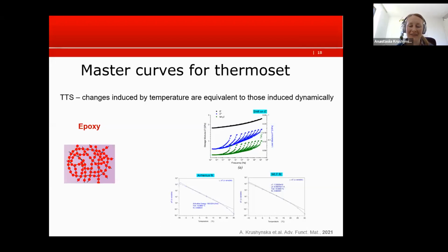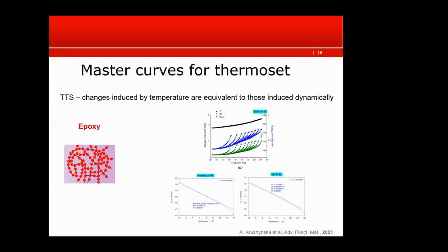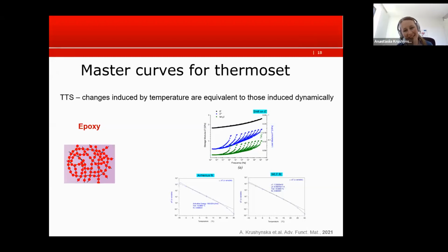And actually, the impression that you got by looking at this data is because these are already clean data. They do not contain high frequency content. So this is already low frequency, because with high frequency, it's a total mess. So to visualize it and to show the trends, they kept only the low frequency content. Maybe they could reduce it further, but here the idea was to illustrate that even by preserving nice values, we cannot obtain a good master curve. And yes, you're right, here is a shift for storage modulus, but we did the other shifts too, and we got the same messy curves.